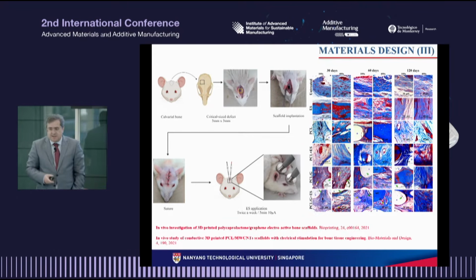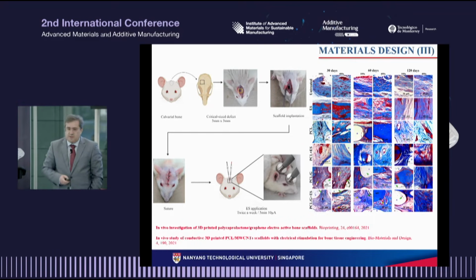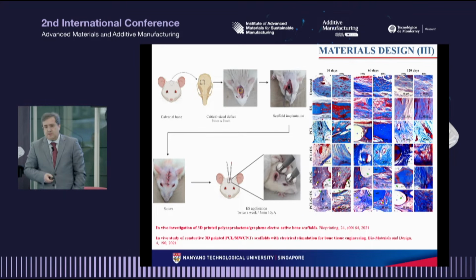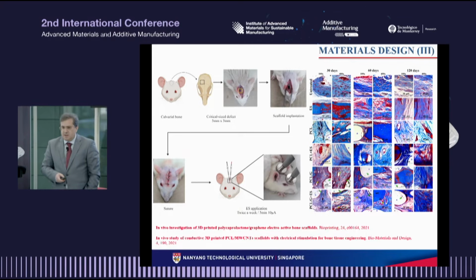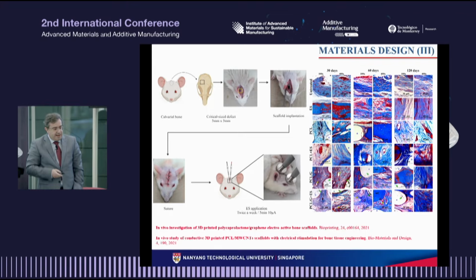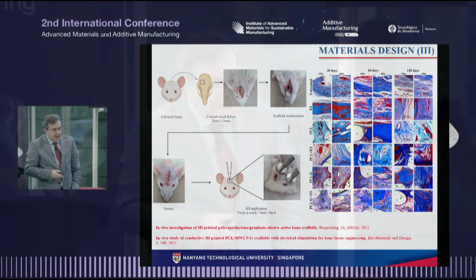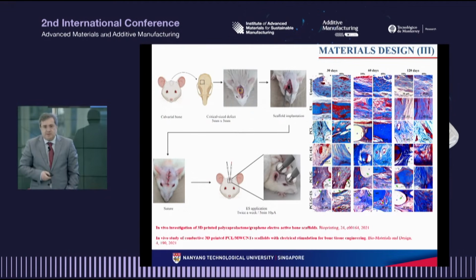So we designed these scaffolds containing biodegradable non-conductive polymers and certain amounts of conductive materials. And we use multi-wall carbon nanotubes or graphene. It was important to identify the critical value of these conductive materials to avoid any cytotoxicity. And we tested in the lab and also preliminary tests with small animals, rats.